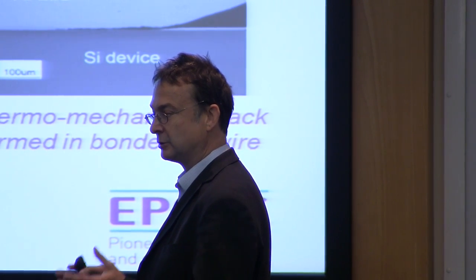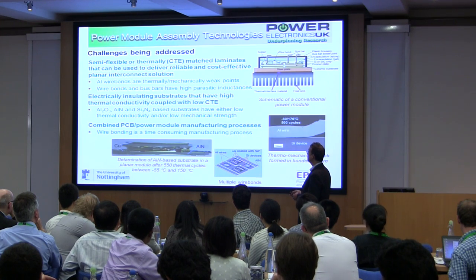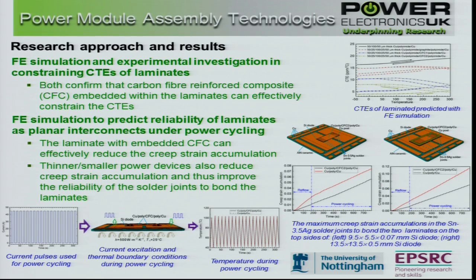This particular work package is about exploring novel ways of improving those two problems. The first work that's been going on has been looking at the use of carbon fiber-reinforced composites as a form of laminate packaging material. The great thing about them is they have better, more compatible thermal behavior. There's been considerable work on simulating performance and testing at a sample level.